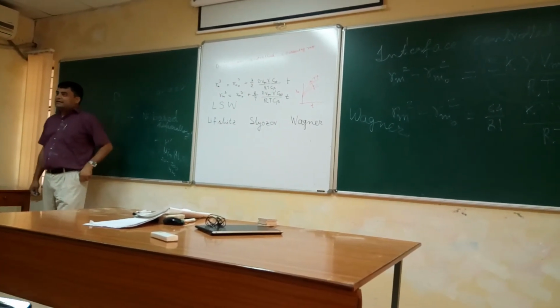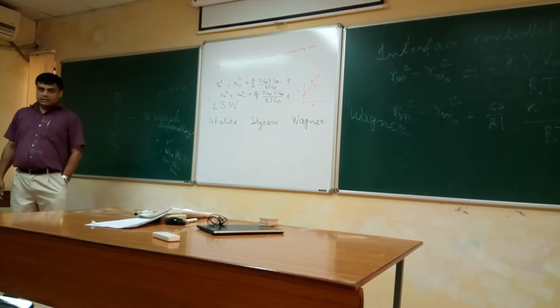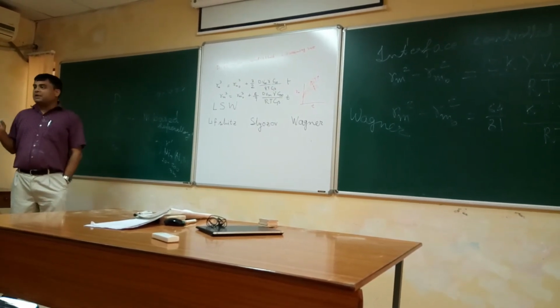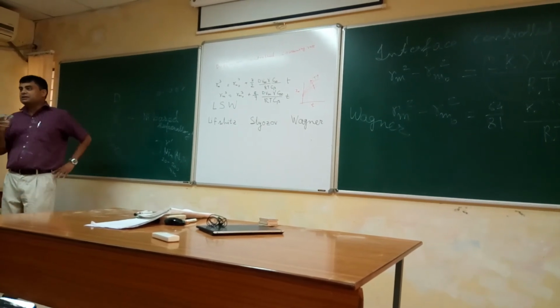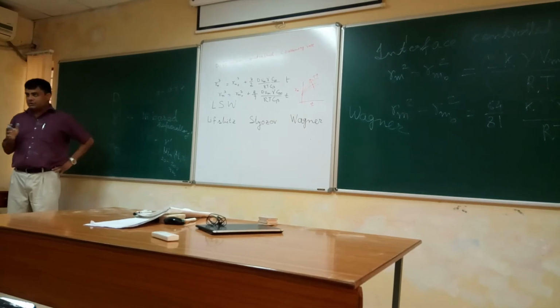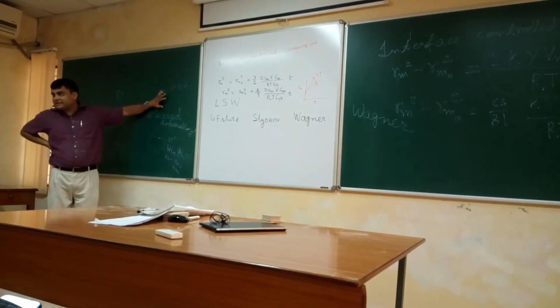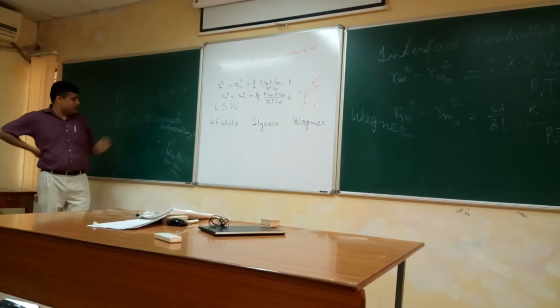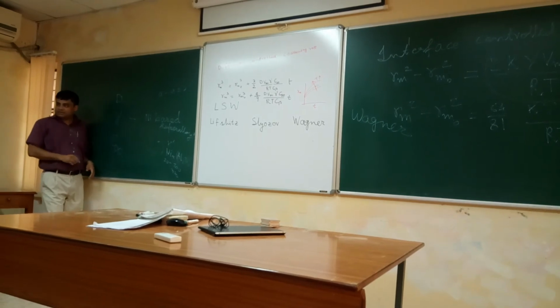It actually increases the creep rupture life by 50 times. Creep rupture life means at that temperature, under that stress, it should not coarsen. So life will be longer if you can resist the coarsening. So coarsening is resisted by lowering gamma in this situation.